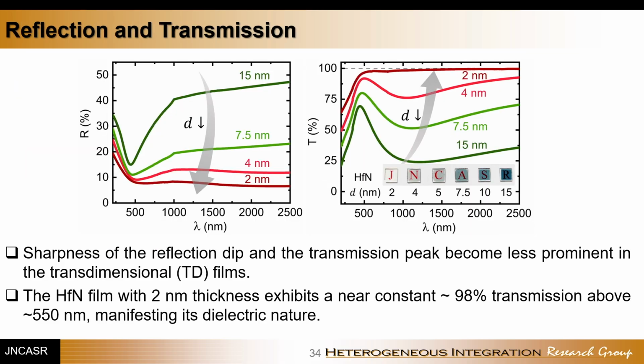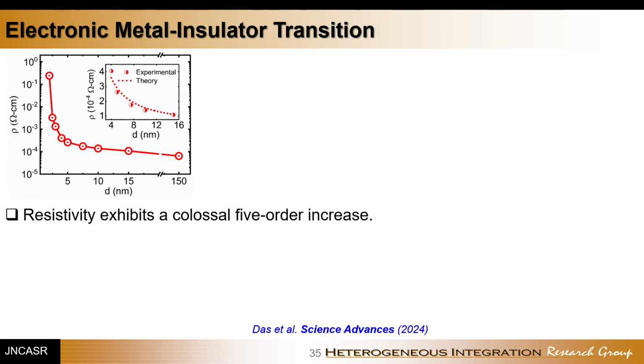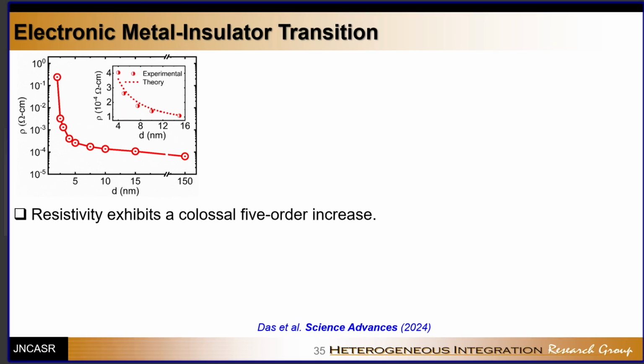This shows up in macroscopic measurements of reflectivity and transmission. Also, in the case of reflectivity, as you see, the 15 nanometer film shows a nice dip near the plasma frequency, but as you reduce it to 2 nanometers, it is sort of flat, underscoring an almost dielectric nature. It shows here also. This is the 2 nanometer hafnium nitride film, looking perfectly like a dielectric. This is further verified by electrical transport, a large change in electrical resistivity also.